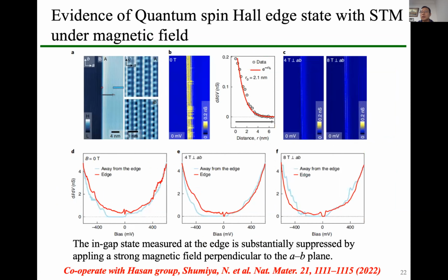Then we cooperated with Professor Hasan's group. We use a strong magnetic field and variable temperature STM to study the quantum spin Hall edge state of this bismuth bromide. We found that the bulk exhibits a very large gap here, about 200 meV. These experiments used single crystals, not nanowires. But if we measure the dI/dV spectra at the edges, then we can find that there are some in-gap density of states here.